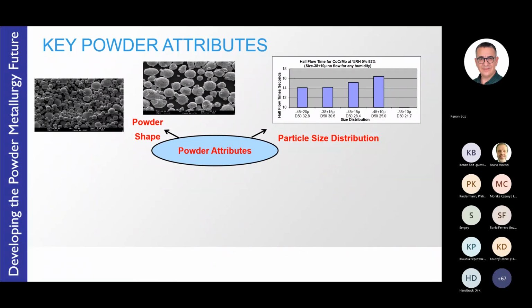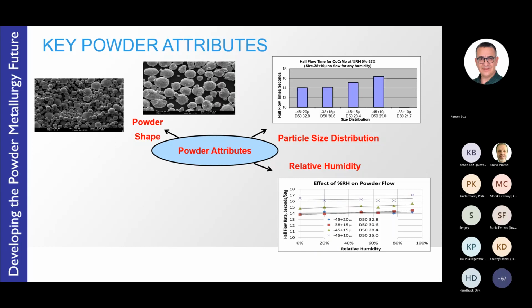Issues such as humidity, and the Euro AM has a project which is starting to investigate the effect of humidity and flow characteristics. Here, we can see the different size distributions and the effect on Hall flow rate. As the average size drops, typically the flow of the powder becomes poor until effectively, if you try to measure it by a Hall flow meter, it becomes very difficult, if not impossible.